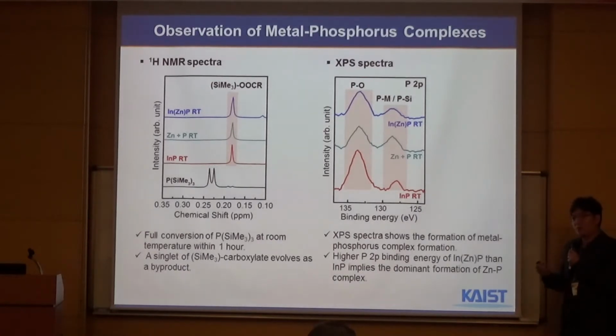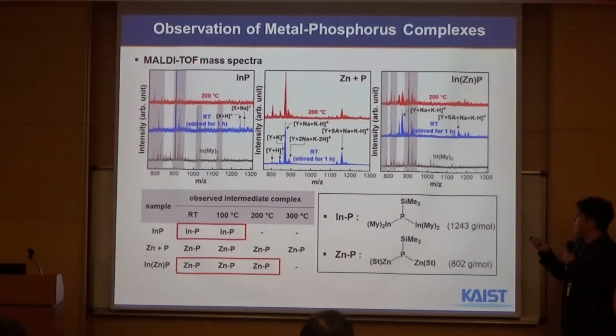We ran a lot of different characterizations, so the following slides may be a little redundant, but we have NMR spectra and then mass spectroscopy data. In the MALDI-TOF mass spectra, when zinc is introduced, there is now a new set of chemicals formed, indicating the formation of zinc and phosphorus bonding. Instead of indium and phosphorus bonding as an intermediate species, you now get zinc and phosphorus bonding, which replaces the phosphorus precursor intermediate species. The reactivity of this is a lot slower than the reactivity of the indium phosphorus intermediate species, and it's going to slow down the reaction.